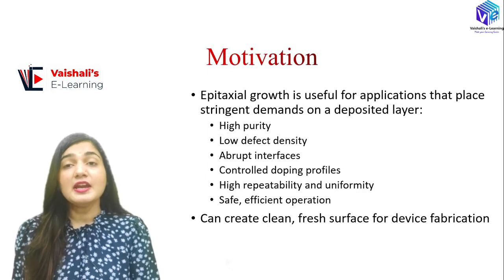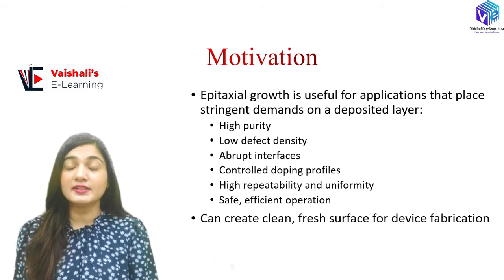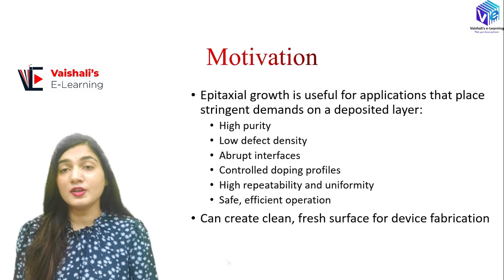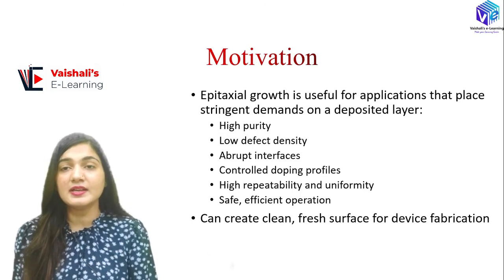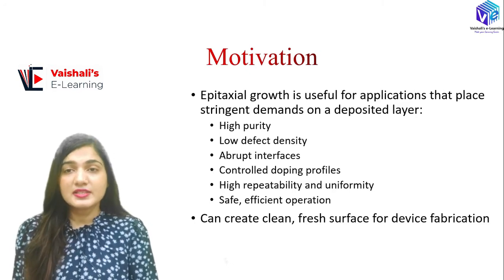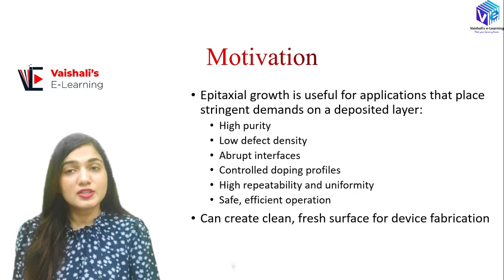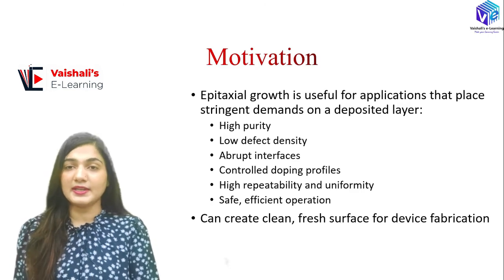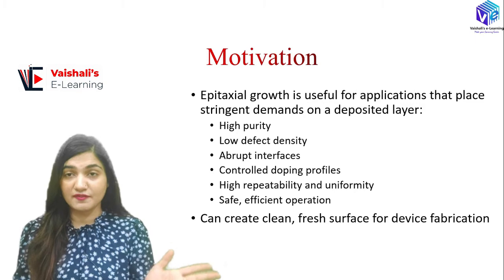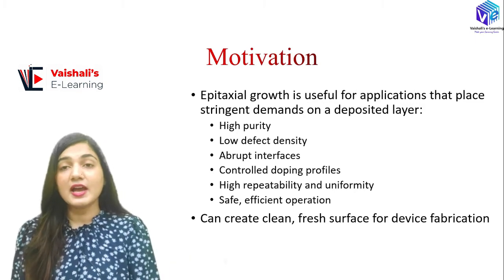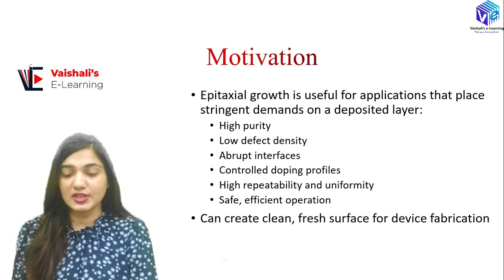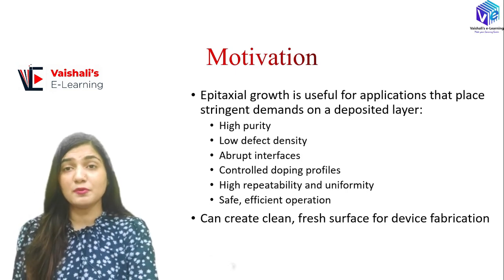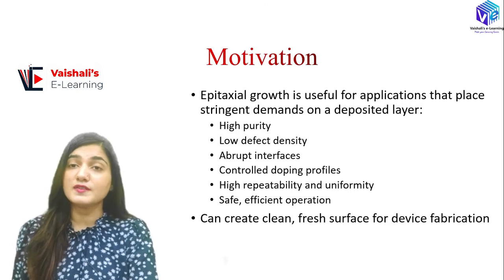The defect density is very low in the epitaxial layer. When we cut a wafer from the ingot, there are many defects. Even after shaping, cleaning, and processing, some defects remain on the surface, which we minimize with the epitaxial layer. The epitaxial layer surface is defect-free. Additionally, the interfaces are very abrupt in the case of the epitaxial layer, and the doping profile is very controlled.